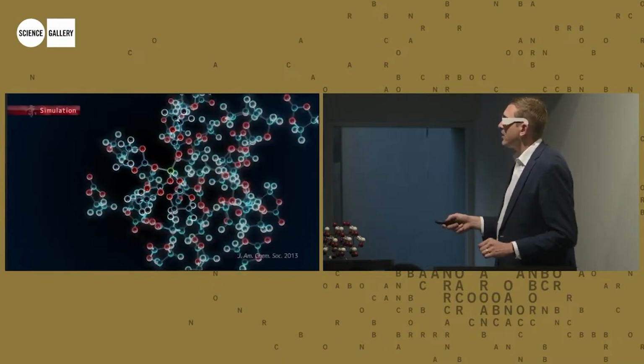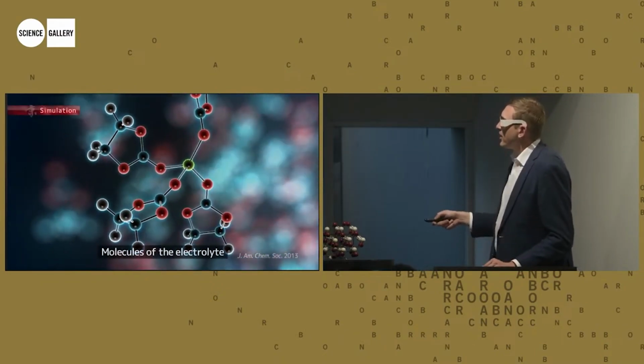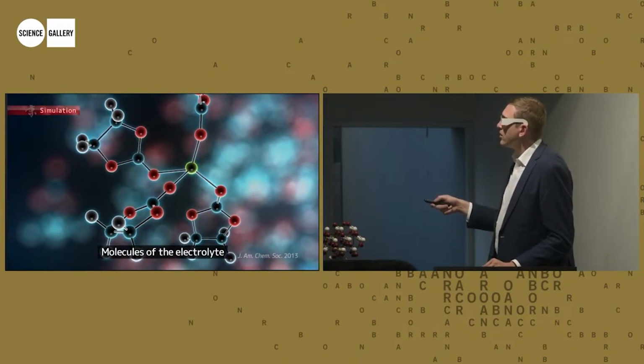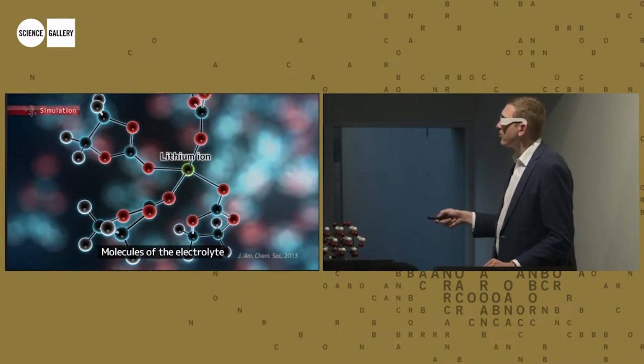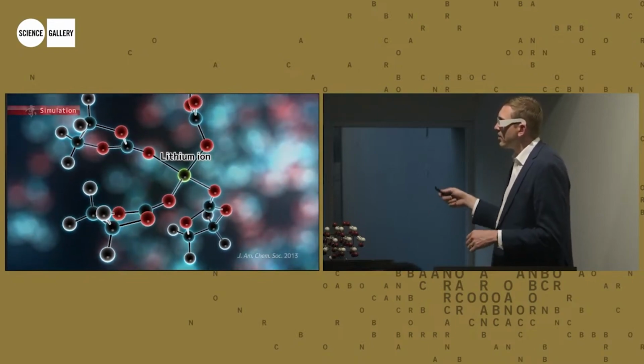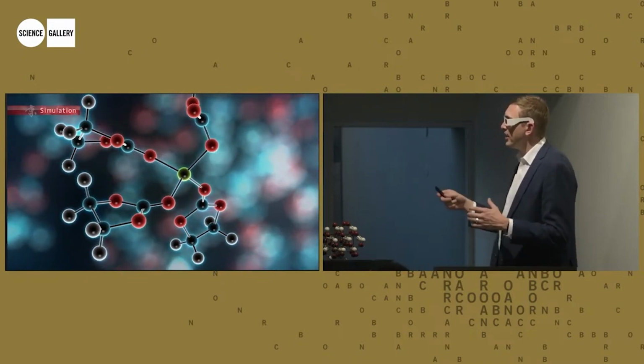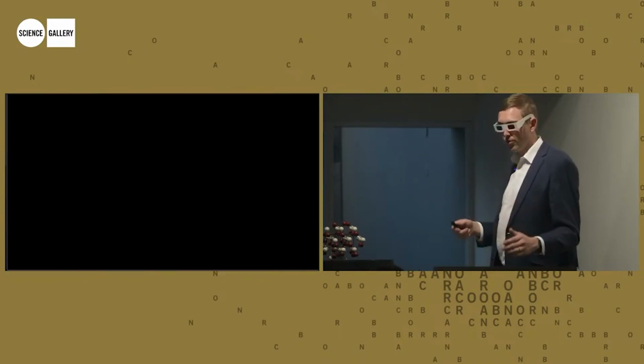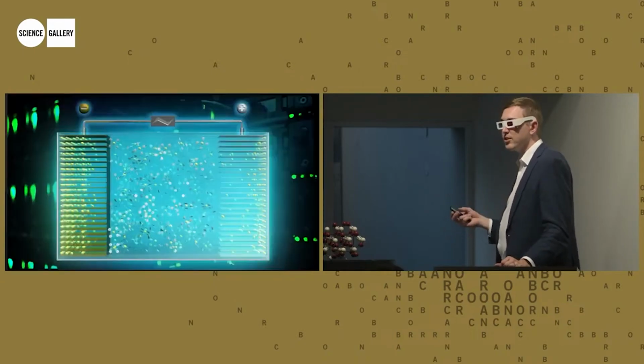This here is a simulation that was done, and the reference is down here. These are the molecules that are in the liquid that hold onto the lithium ion. So you can see these molecules here, and they pass the lithium ion from one molecule to the next, allowing it to travel through the electrolyte solution, which is just a salty solution.